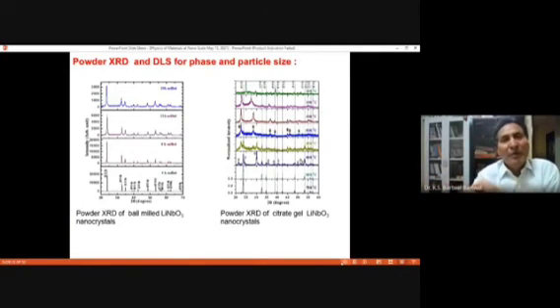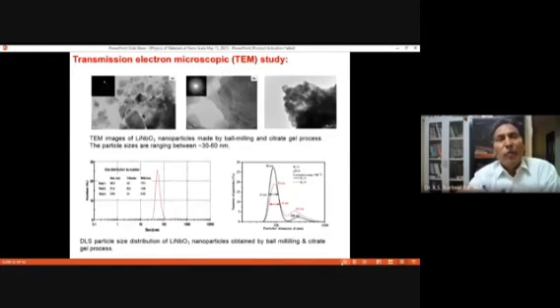Then finally you tell that, okay, this is the lithium niobate, this is the size, this is the particle size, and then only you can go for any application of that material. Then you have to have transmission electron microscopy of those developed materials also, because you have to have single crystal, single phase. If it is a single crystal, fine.